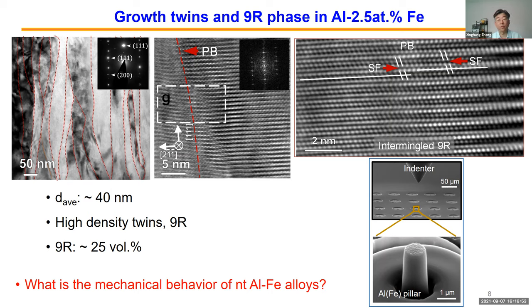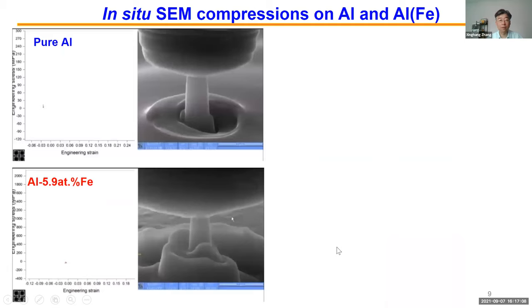Does that change the mechanical strength of this aluminum? Because the film is normally pretty thin, a couple microns, 20 microns at most, you can make pillars coming out of this and then perform compression tests. So this is a compression comparison with pure aluminum, using a diamond flat punch.